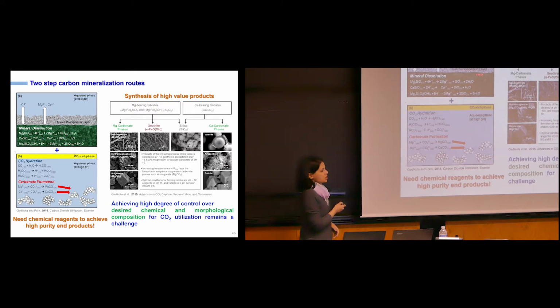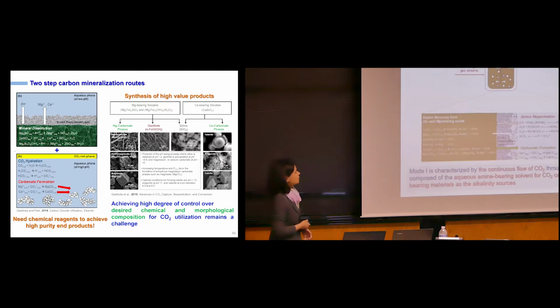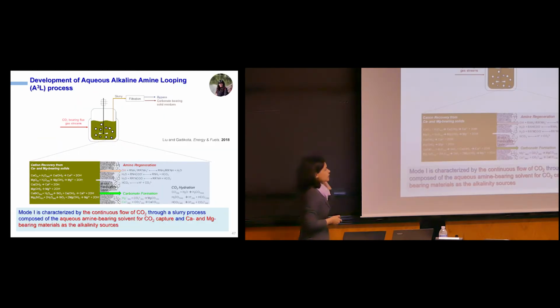Here we basically leach out the calcium and magnesiums and then bubble CO2 through to produce high purity calcium magnesium carbonates. This is of a lot of use for a lot of commercial applications, but again, a lot of consumption of acids and bases. Can we do this in a slightly more elegant manner? So my student, Mission Liu, and I, we came up with this approach, which is known as the aqueous alkaline amine looping approach. It's a mouthful, but here's what we're trying to do.